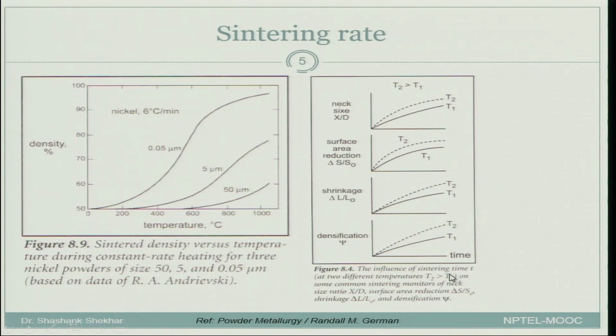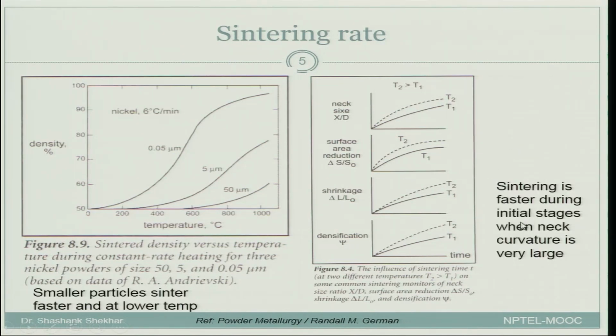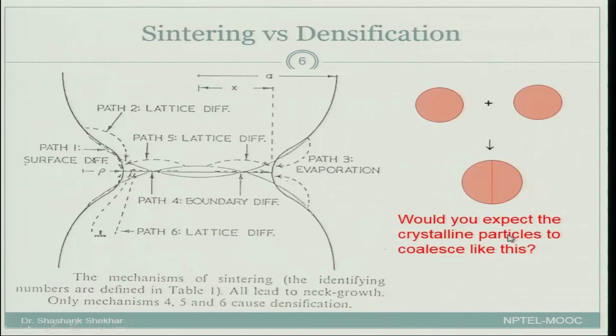So, overall we have seen that sintering rate depends on particle size. Smaller the particle size, higher the sintering rate. It depends on what stage you are at. Initial rate is much higher. It depends on the temperature. Higher the temperature, higher is the sintering rate even in the initial stage, and you reach a much larger saturation value. So, sintering is faster during initial stages when neck curvature is very large.